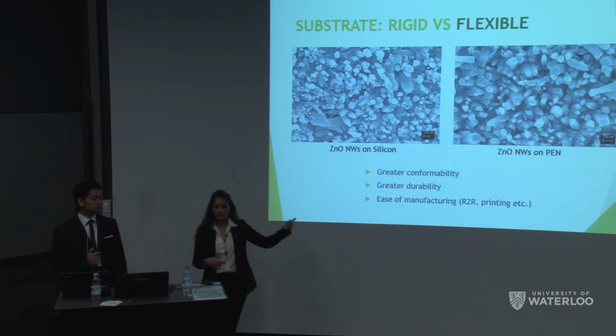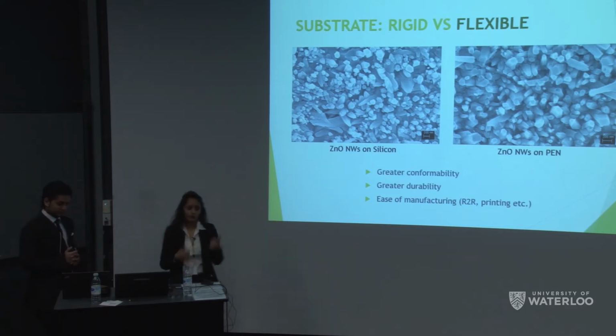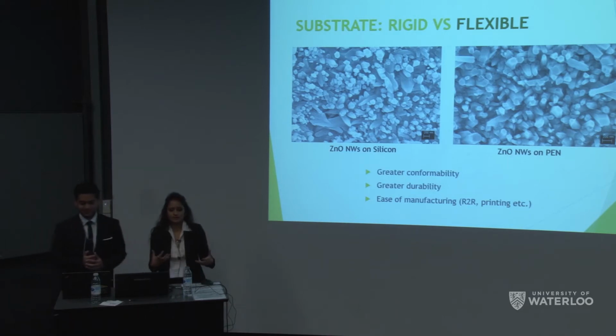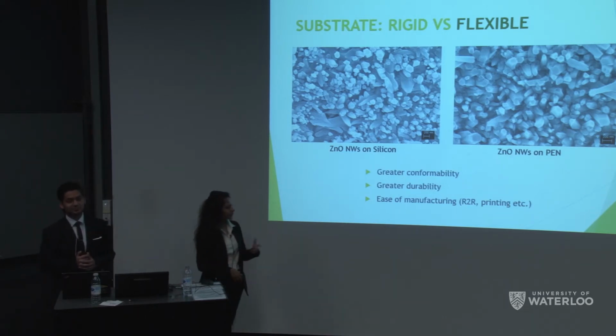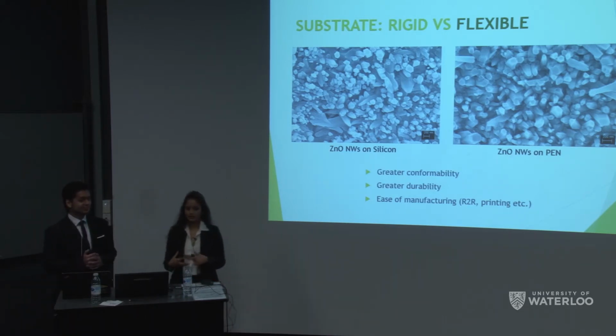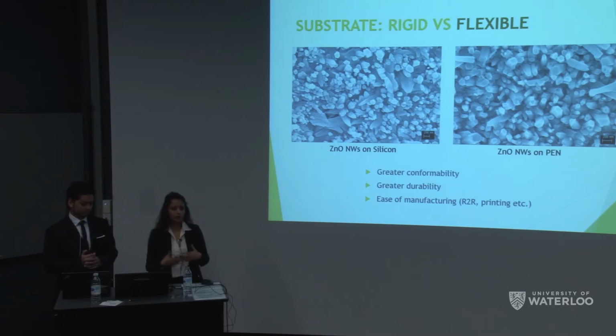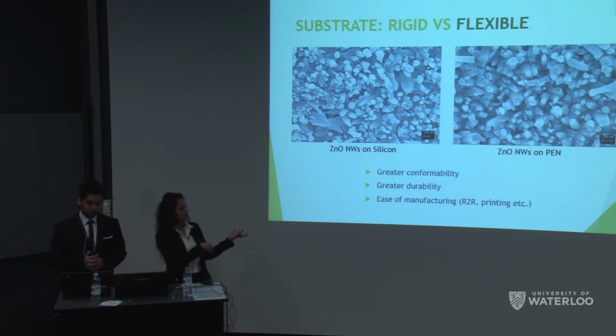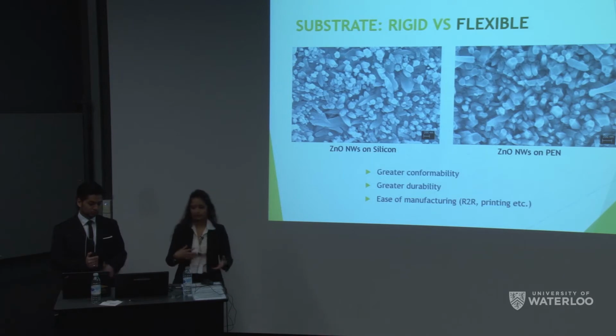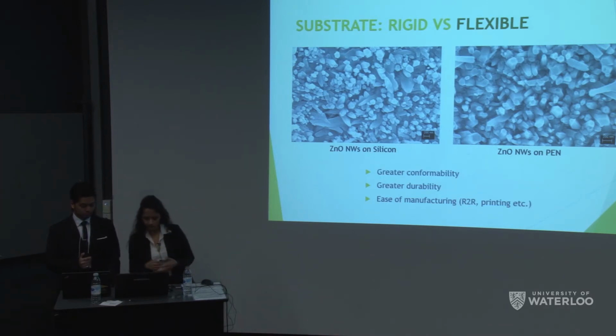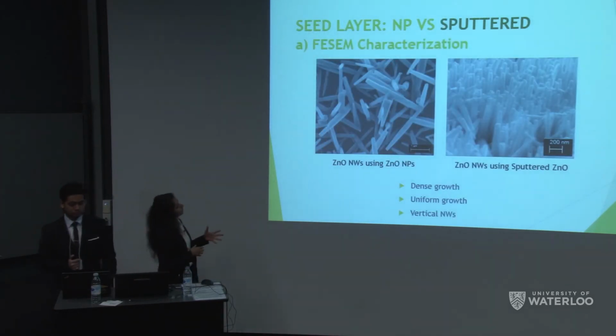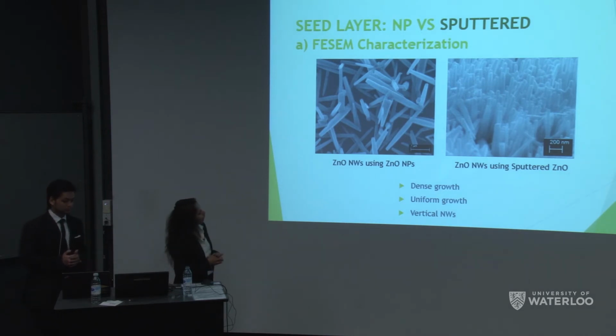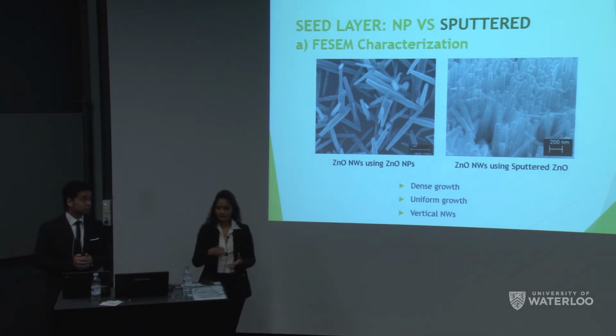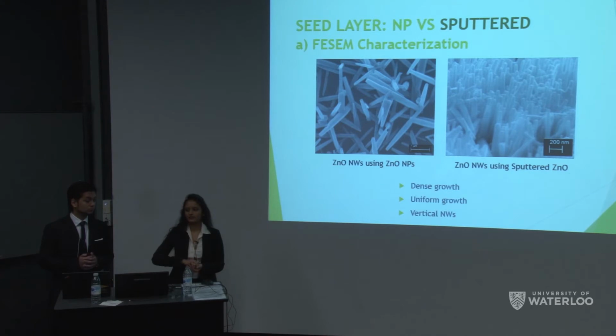And the reason why we went ahead with the flexible one is because it can conform better. It would probably be more durable than something like glass or silicon. And with new manufacturing technologies like R2R and printing coming up, we could possibly see this being easy to manufacture in the future. The next consideration was our seed layer, which is key for the growth of the nanowires because these act as nucleation sites from which the wires crystallize and grow.